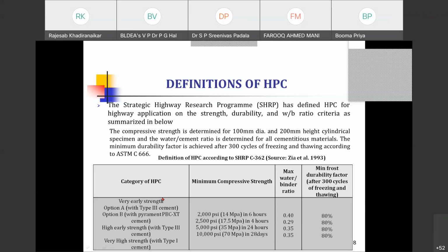The compressive strength is determined for 100 mm diameter and 200 mm height cylinders. Earlier, we were strictly adhering to the bigger size, that is 15 centimeter diameter and 30 centimeter height cylinder. But it has been found later that even if you go for smaller sizes, maintaining an H/D ratio of 2, you get reliable results. So that's why they used 100 mm diameter and 200 mm height cylindrical specimens.